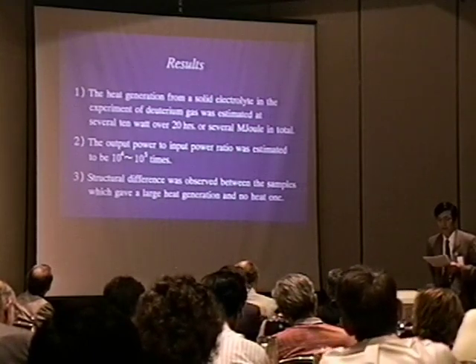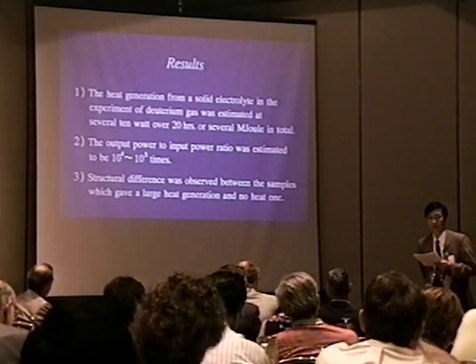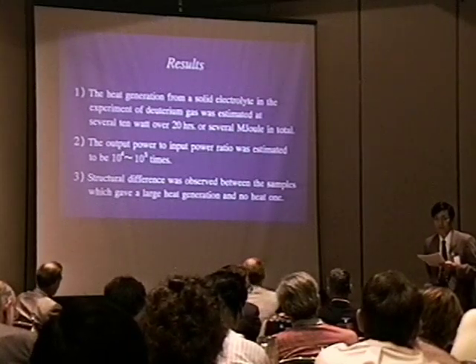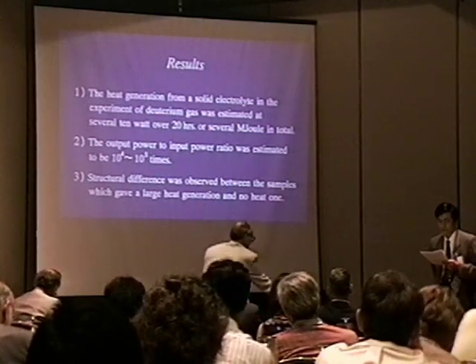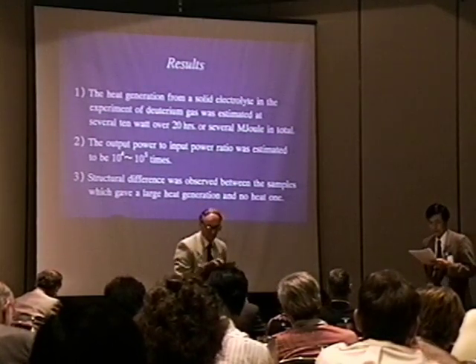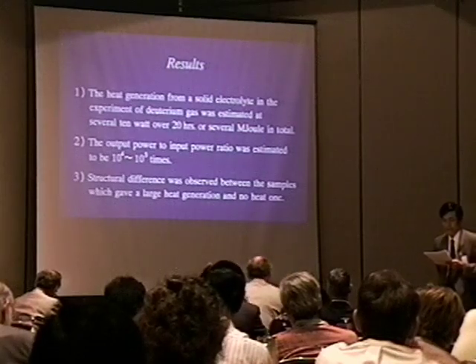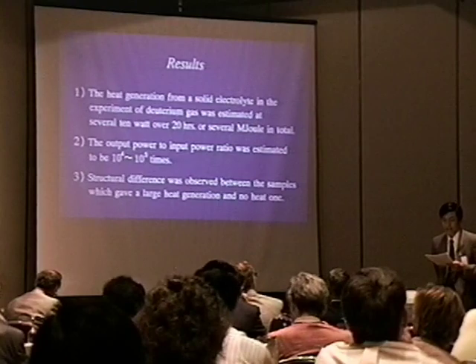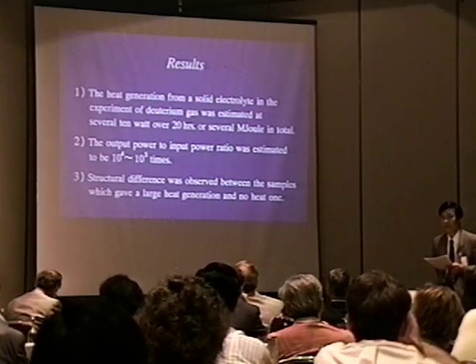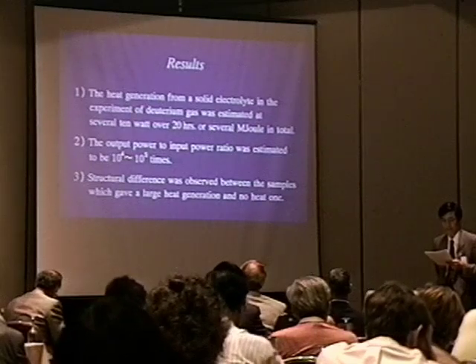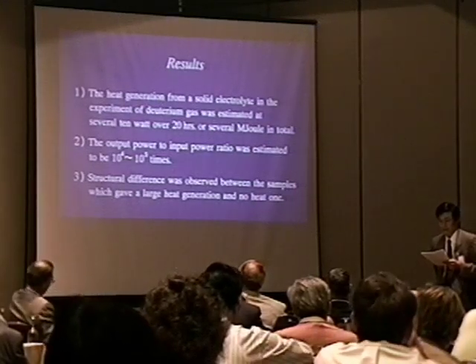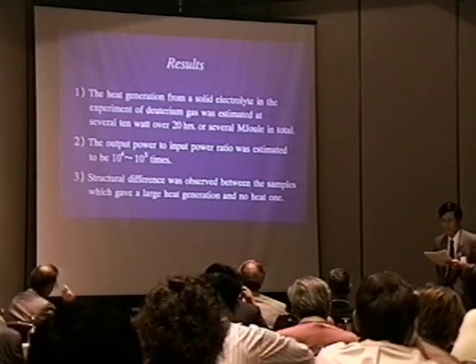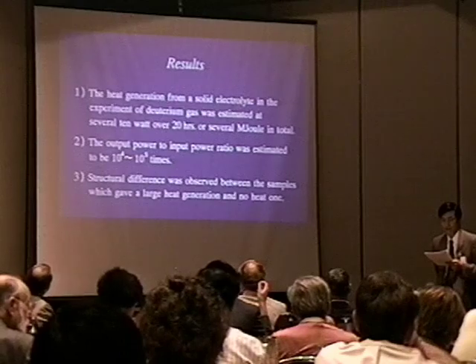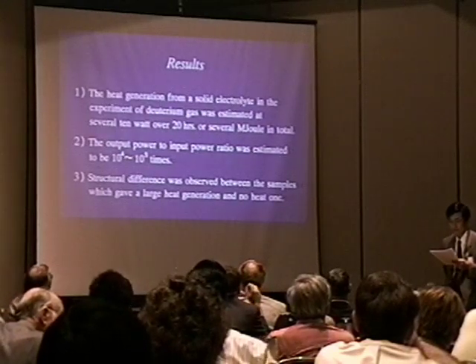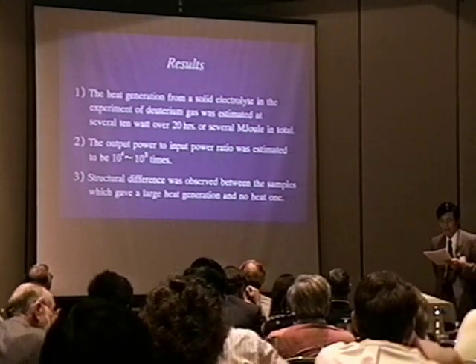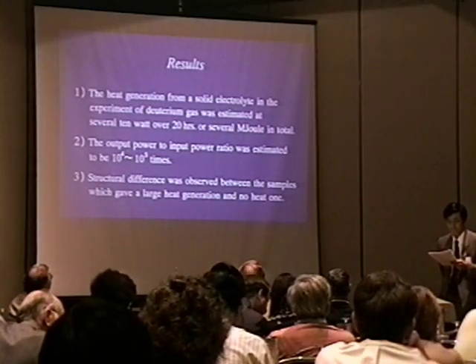We have tried to detect gamma rays using a handy type detector, but no radiation was detected. Nevertheless, we have to use a more precise detection system before drawing any conclusion. If we assume that all the heat evolution is caused by fusion of 2 deuterium atoms yielding 1 helium atom, less than 1 cubic centimeter of helium may be generated, as compared with typically 100 cubic centimeters of deuterium gas. Nevertheless, we may have a chance to detect helium nearby a large device. Thank you for your attention.